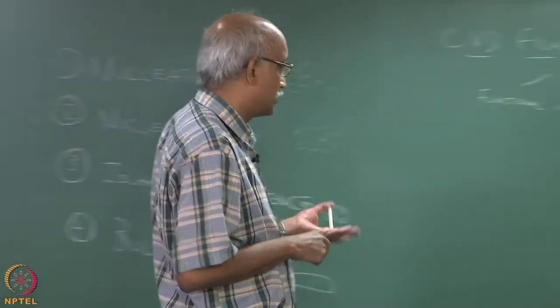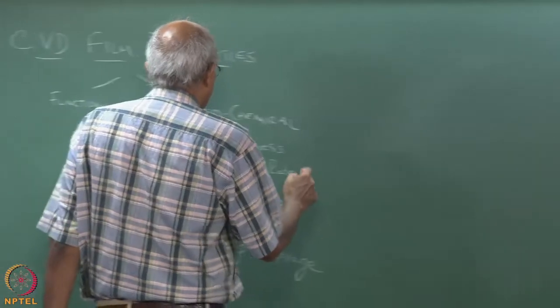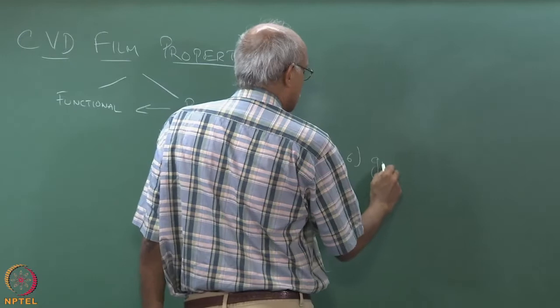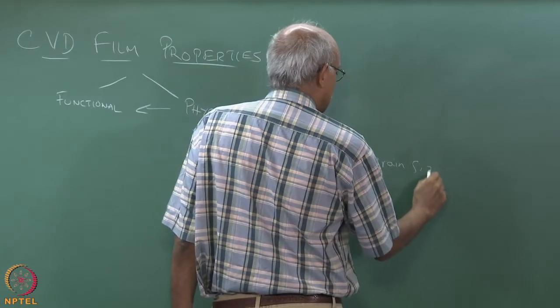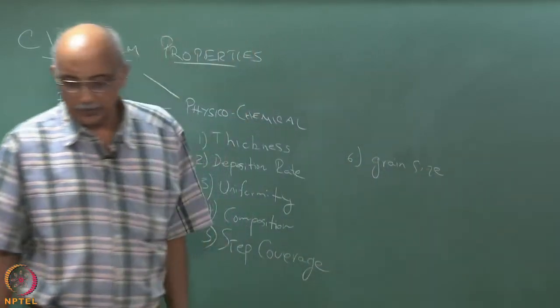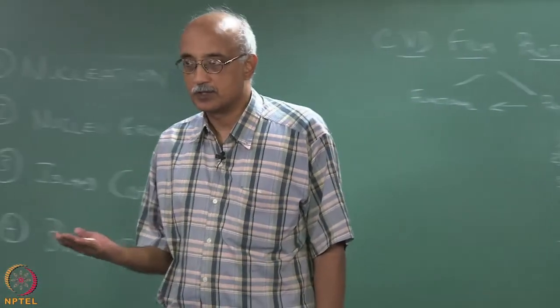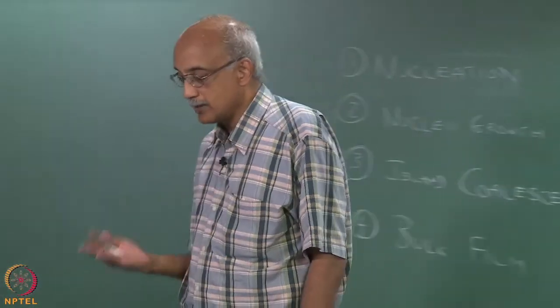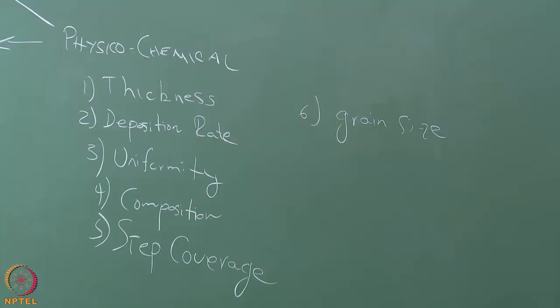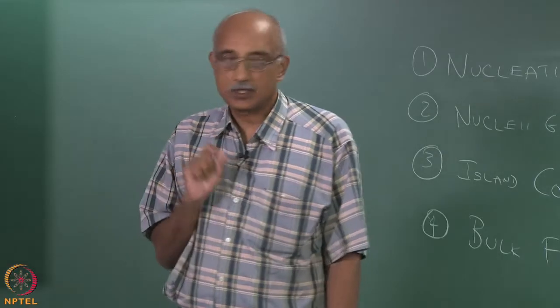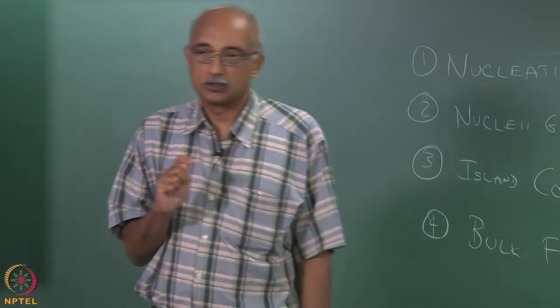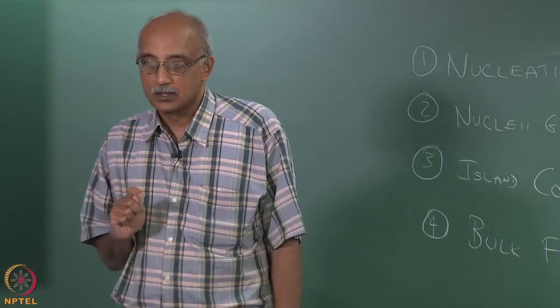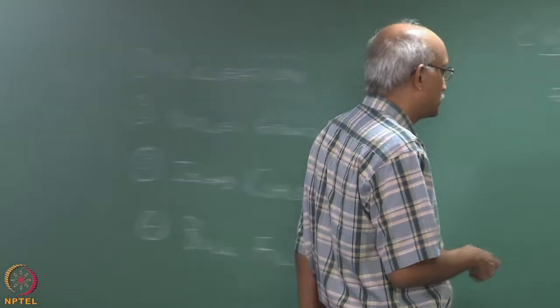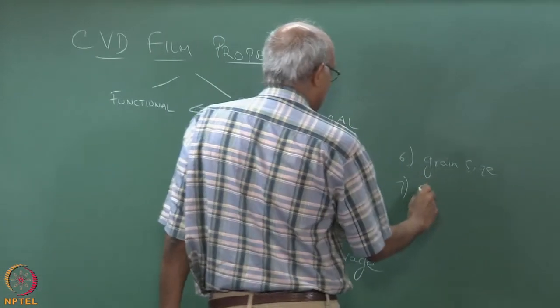So what are some of the other properties? Grain size. Particularly when the durability or integrity of the film is a very strict requirement, the grain size plays a huge role. You want to, in CVD processes, achieve as fine a grain size as possible, mostly. So you have to have some control over the grain size that you're achieving. Now, grain size is also related to the stress level on the film.